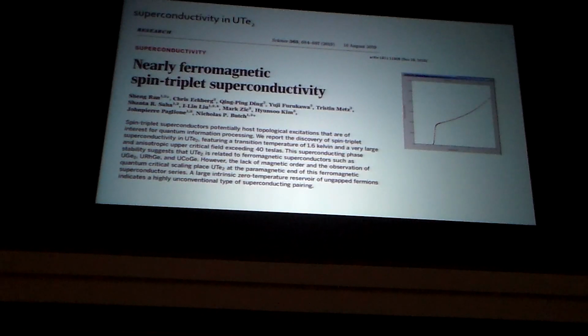Okay, enough about high TC superconductivity. There are other things going on in the field of superconductivity, and I wanted to highlight some of the work done here by Nick Butch and Johnpierre Paglione, which has to do with the discovery of a spin triplet superconductor. Now, spin triplet superconductivity is very rare. Helium-3 as a liquid is a triplet superfluid. It's been known for a long time. But unfortunately, we're not going to be able to use that in any way.